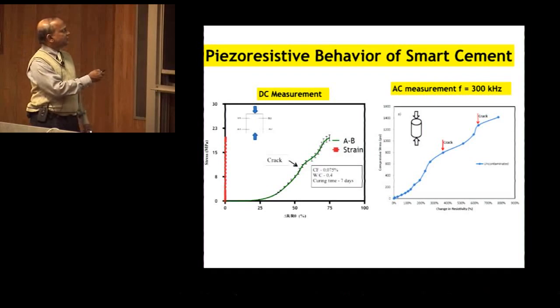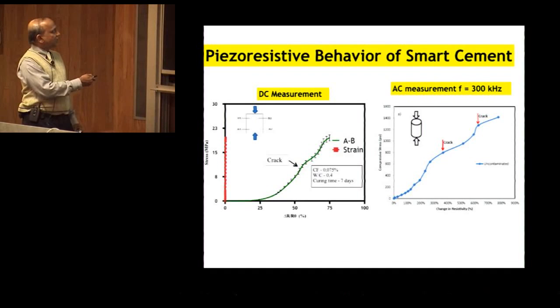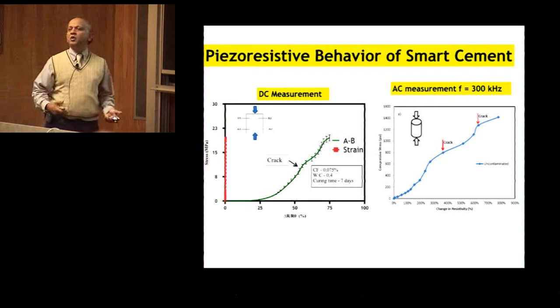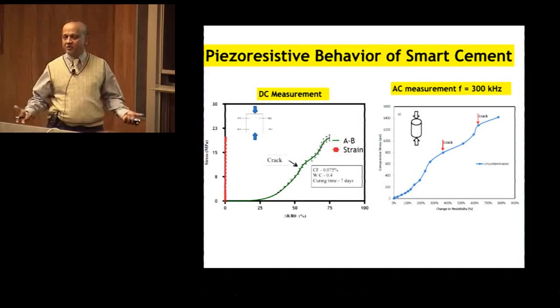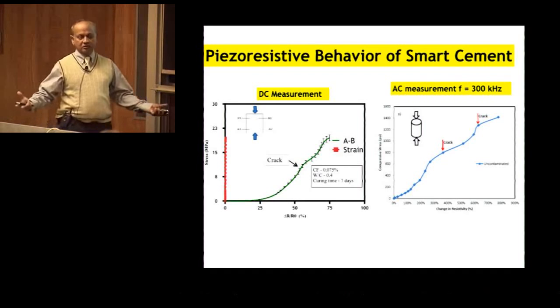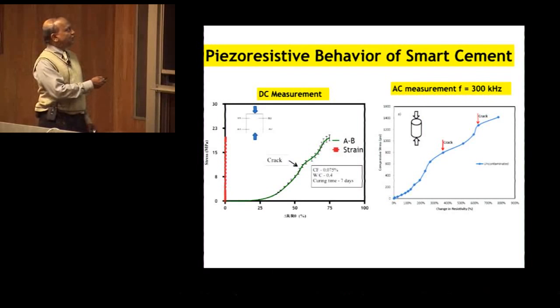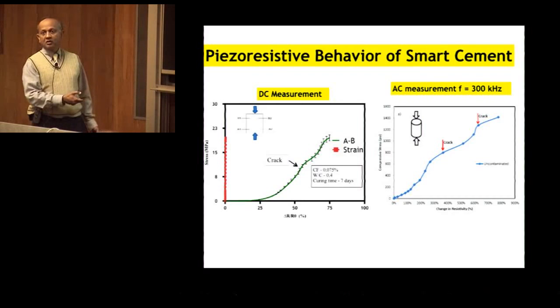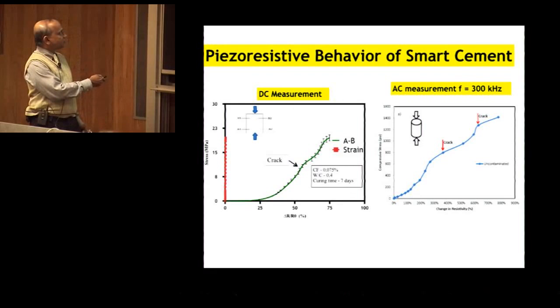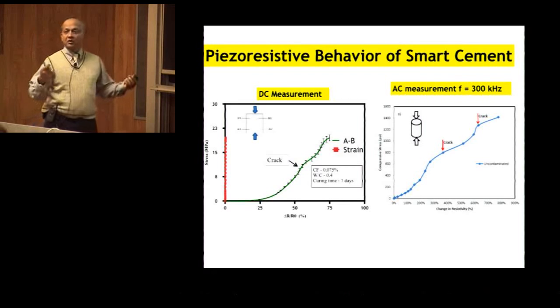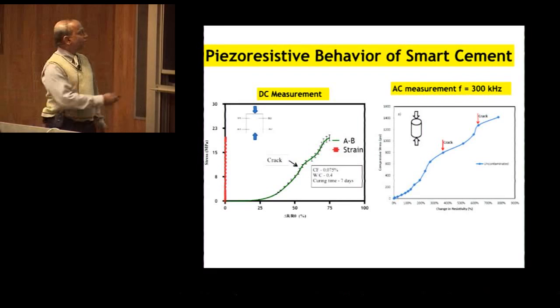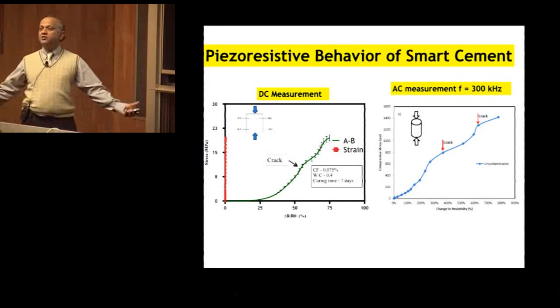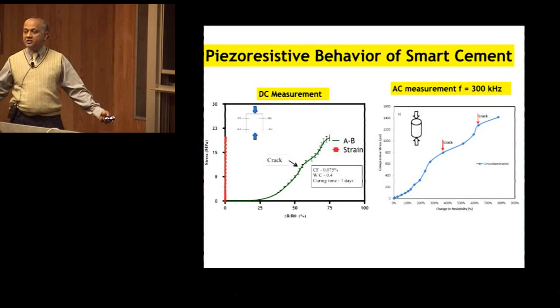You can look at the stress resistivity change, and also I have plotted the stress strain. The strain for the cement at failure is about 0.2 to 0.3%, and it fails straight. But if you go to the resistivity change, you are looking at a change of about 80% or more for the same stress. And at small stresses, you can see how the resistivity of the smart cement is changing. So from the change in the resistivity, we can tell how much stress is on the material. This is what we are doing.